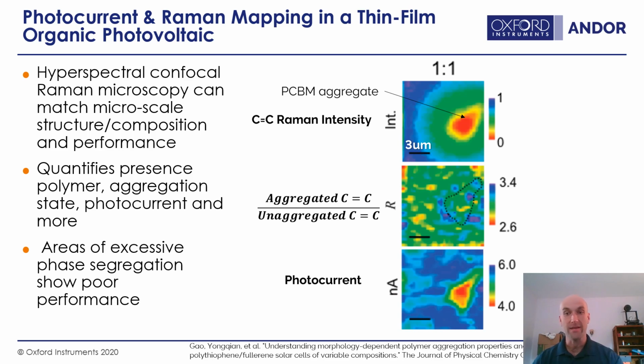So it can quantify the presence of polymer, how much or how little polymer is in a region, because we're looking at the overall scattered intensity. Its aggregation state: is that polymer ordered or disordered, in the sense of, is it collapsed into an aggregated state or not, and how much photocurrent is coming out of that area of the solar cell.